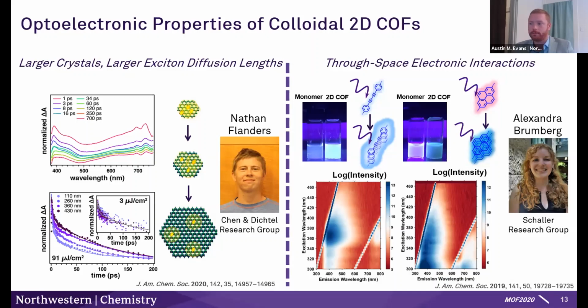And then working with Alexandra Brumberg, we've looked at a lot of through space electronic interactions that arise as a function of the van der Waals contact between two sheets. So for example, we can take these diacetylene units and compress them to really close contact, and that leads to a major enhancement in fluorescence. And similar things can be observed with other chromophores. This is an excimer type emission that arises from pyrene aggregation. And I think these fundamental investigations are key to determining the appropriate application space for different types of 2D frameworks. And I think this is an exciting way to be able to study that in a systematic way.